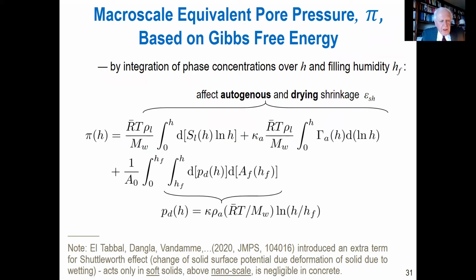All right, so to get the equivalent pore pressure, we have terms which are shown here, associated with autogenous shrinkage and drying shrinkage. Liquid water here, this is the capillary part. Liquid water again here, this is adsorption, the thickness of the adsorption layer. And this is for the fully filled pore where you have disjoining pressures. So pressures can be calculated, and they are here. They can be calculated if you know the ratio of transverse and longitudinal pressure. That has to be estimated.